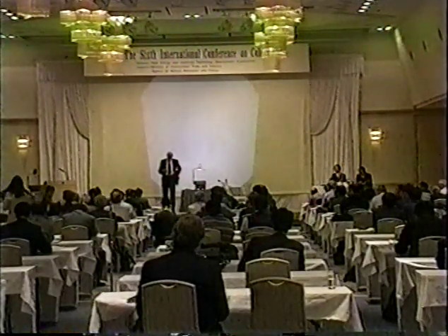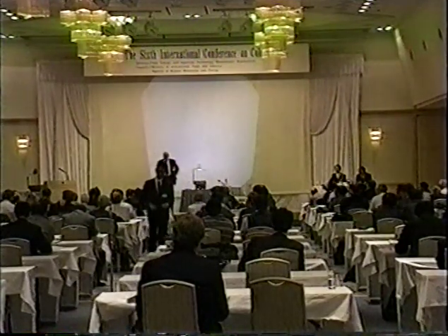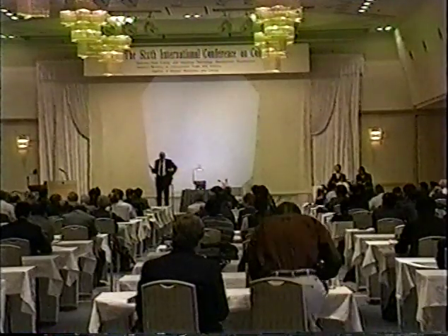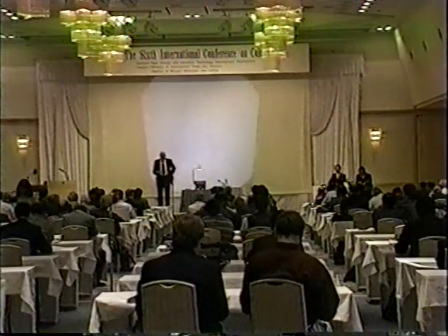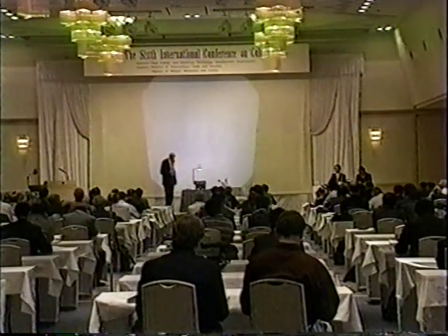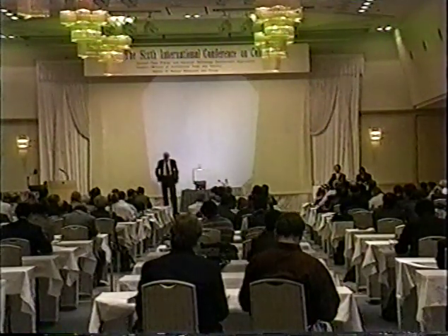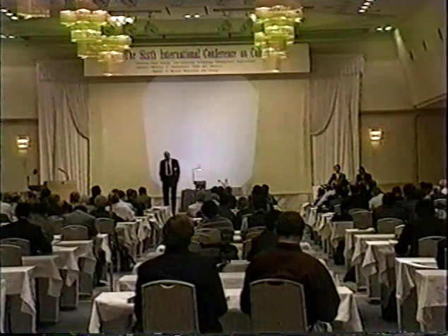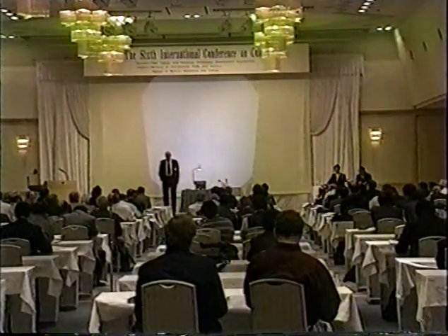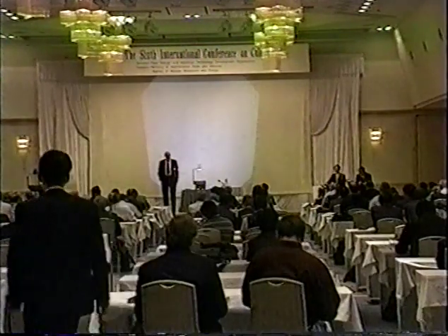Dr. Chow? I'm just curious, how much heat did the electrode produce? 0.56 megajoules, and that's about 65 megajoules per mole of palladium. And by the way, I was able to measure by the ratio of the gamma rays that boron in this particular sample, boron-10 anyway, was 20 parts per million by weight. The total boron was presumably 100 parts per million, a very frequently observed number in palladium, I guess because everybody's always adding it in the final form.